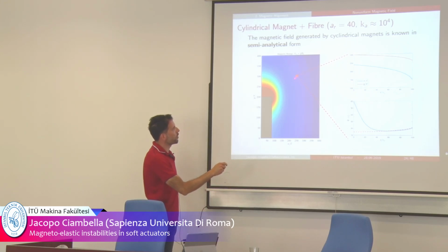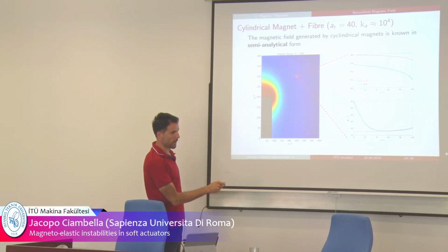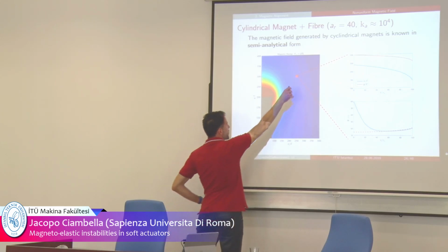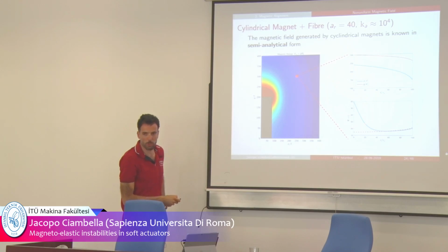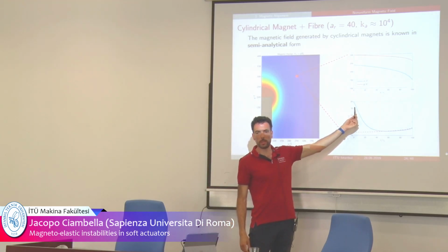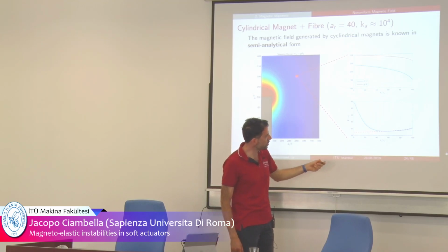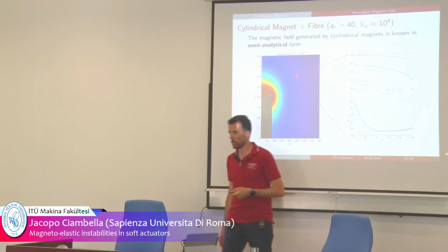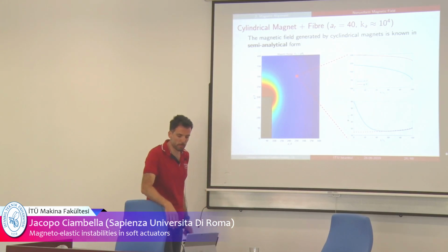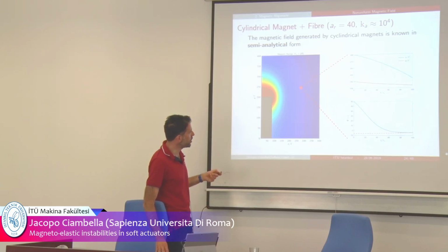And so this is what happens when you have a particle here, initially in this position, and what I plot here is the position x and y with time. So this is 0, 0, meaning that, as expected, both x and y diminish. Okay? So the particle is being attracted by the magnet with time. And here is the orientation of the particle, and this is the direction of the corresponding field line. So what is happening: the particle starts with a certain orientation, 60 degrees, and with time, as expected, it orients parallel with the field line. Okay? So this model predicts this behavior, which is quite reasonable. Different position, different behavior, of course. And the nice thing is that everything here is in closed form.